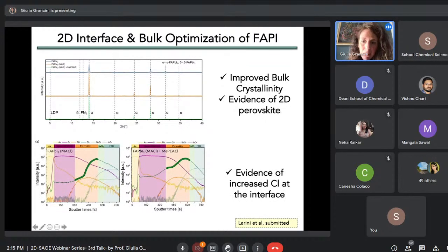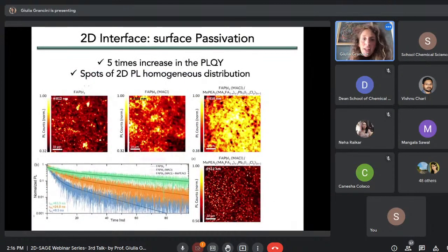Also, another evidence of it comes from TOF-SIMS measurements, time of flight secondary ion mass spectrometry measurements, where you can see that the chlorine content at the interface between the perovskite and the spiro increases when you have this phenylethylammonium chloride 2D-based perovskite at the interface. So, you are creating this interface, and what is happening? Well, from a physical chemistry point of view, when you map the photoluminescence signal of your combined 3D-2D system, there is a 5 times increase in the photoluminescence, and in particular in the photoluminescence quantum yield, showing also a very homogeneous distribution of the emission from the 2D perovskites.